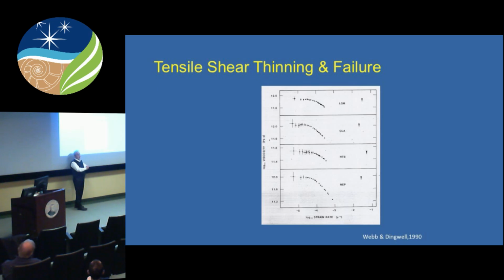That was Newtonian viscosity. It means that the value of viscosity, which is obtained as the ratio of the stress to the strain rate, is constant regardless of the conditions of strain rate. But of course, that's an approximation which fails when you approach the glass transition, which is going to make these liquids solids, which are certainly nothing like a viscous material. And the way they die when they approach the glass transition, which is represented here by this little black arrowhead, is that they collapse in their viscosity.